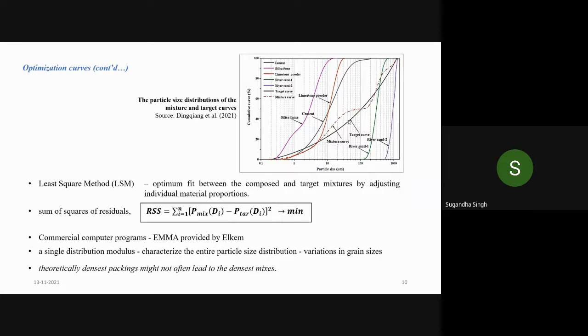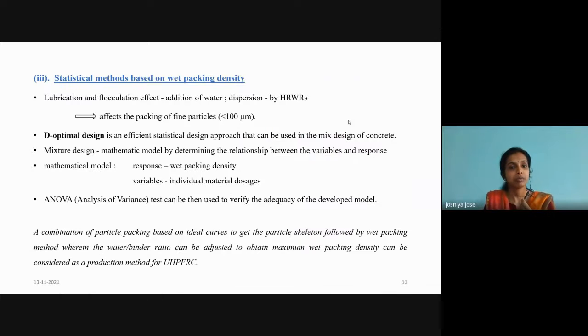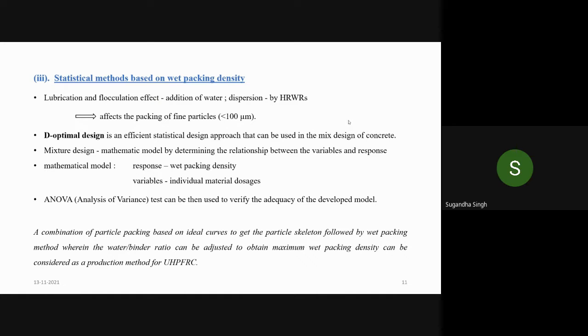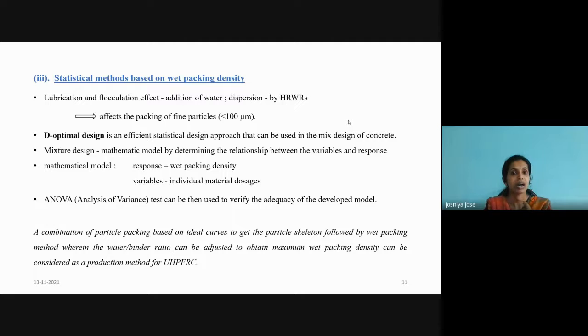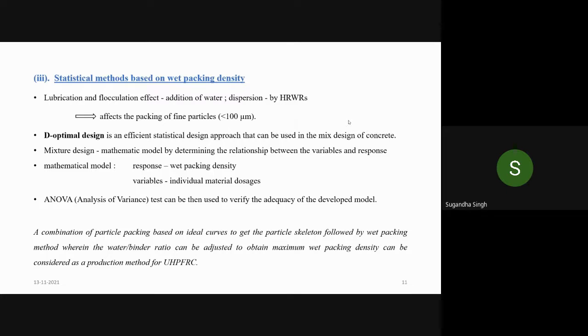But that is the theoretical part, right? Where you do the mix design. Yes. But what about the practical part, where in real life you make sure that the packing density as proposed has been achieved? Ma'am, that can be done by analyzing the wet packing density. That is, the wet packing method can be utilized where we find the particle skeleton from the Andreasen model, and having fixed the particle proportions using this model, we'll vary the water binder ratio and ascertain the wet packing density by varying the water cement ratio. And the mix which gives the higher packing density, we can consider it to be the best one. Okay. But this is still part of mix design, the design part.